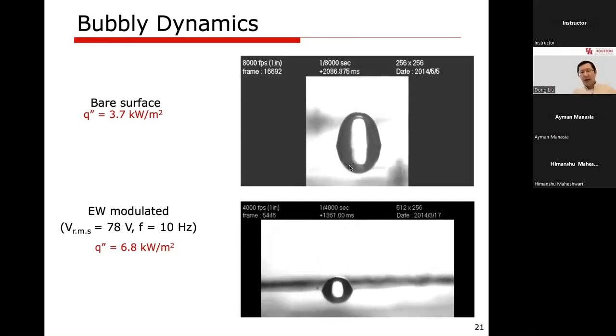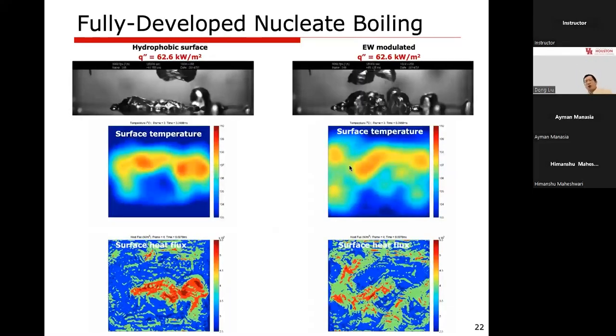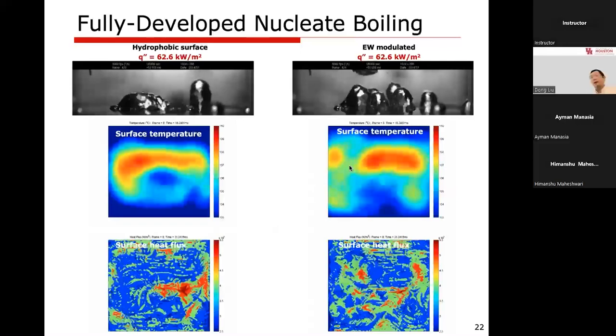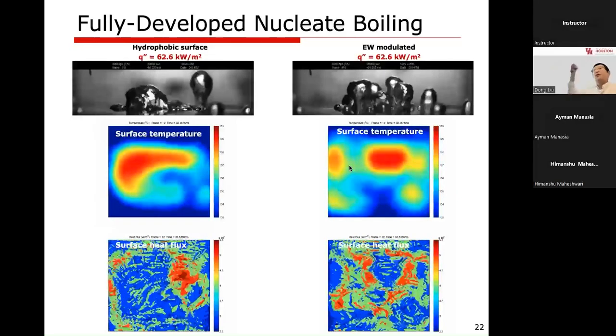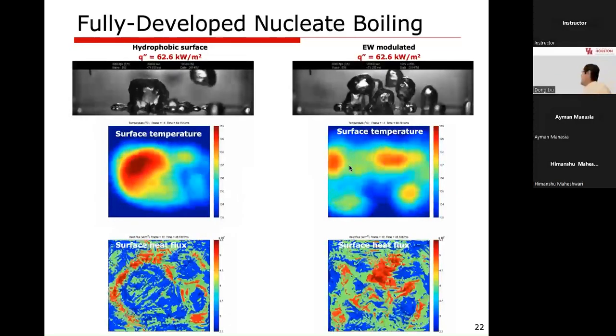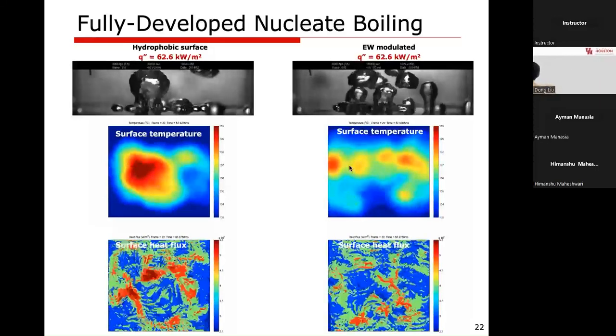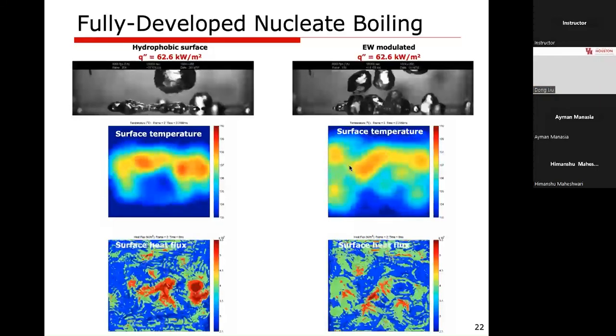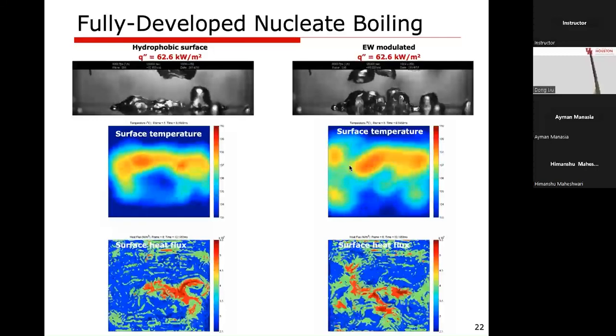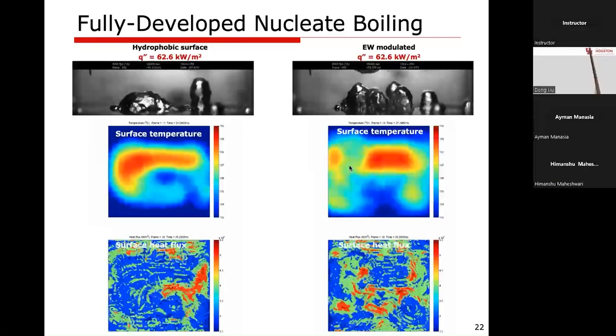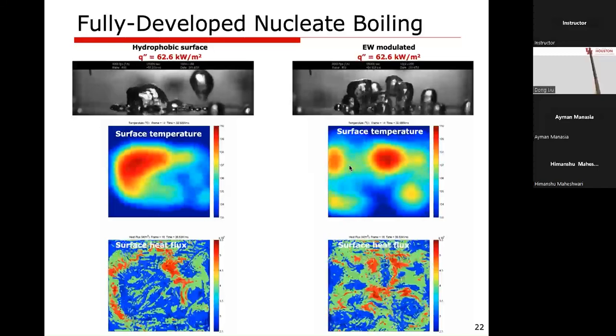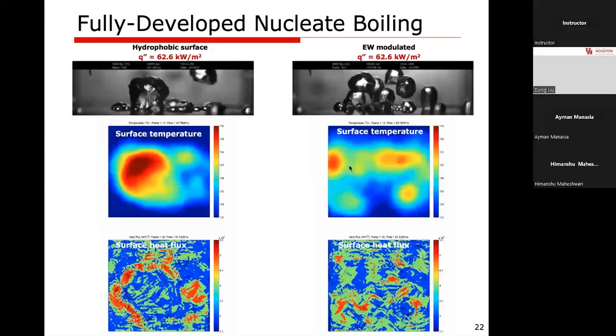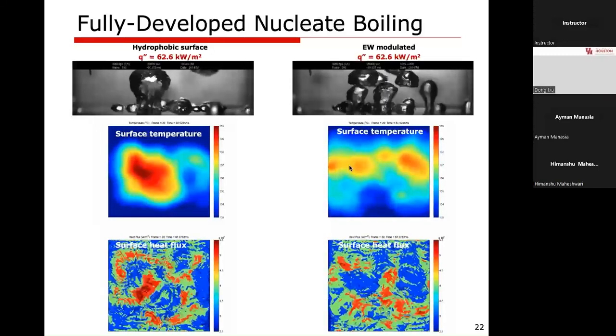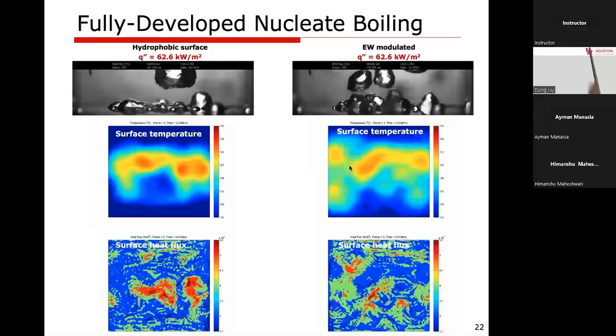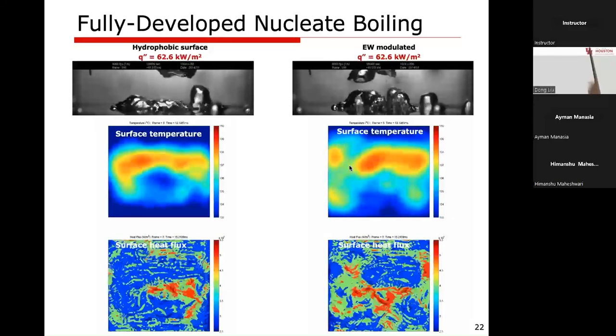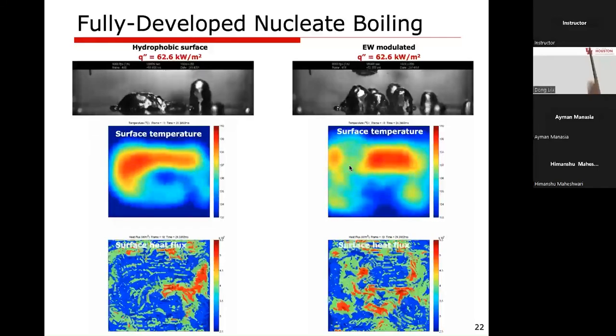Right? Now, in the so-called fully developed nucleate boiling scenario, so this is very close to the CHF, right? So you see, well, look at the videos and images on the left column first. So here at this same heat flux, you see the surface is pretty much covered by a big bubble. Actually, underneath you have a dry layer. And if you monitor the temperature, you can verify. So the maximum reaches about, well, I don't know, 110.